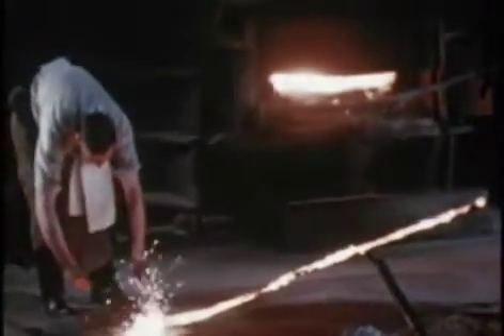The slag, which is a non-metal layer above the molten steel, is formed by additions of ore, lime, fluorspar, or silica sand. This reduces the amount of the undesirable element, phosphorus. After the oxidizing period is complete, the slag, which has absorbed the unwanted phosphorus, is removed. Now, and during the whole refining period, frequent samples are taken for laboratory analysis in order to check the composition of the bath.